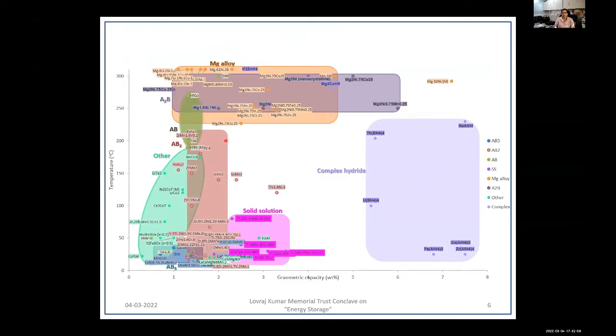Although they have a very high capacity, it can go even up to 7.6 weight %, the operational temperatures are beyond 225 degrees centigrade, 230 or 250 or 300 degrees centigrade. And there are solid solutions which have reasonable capacity, and at the same time reasonable operating conditions, and various other hydrides as well.